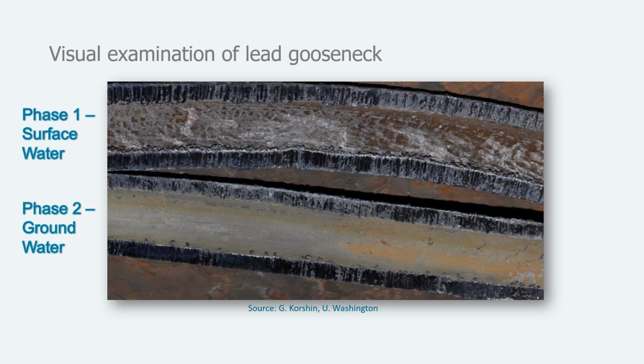So in terms of visual examination, phase 1 on the top, this is one of the lead goosenecks cut in half, and phase 2, where it's all groundwater, we can visually see that the scales had changed and were quite different. What we see in phase 1, the whitish gray, and in phase 2, the whitish grayish colors, typically the lead 2 carbonates, the cerussite and the hydrocerussite, and the brownish orange colors, while they may well be, could be iron manganese. In this case, that's actually lead 4, which can appear as a brownish color.